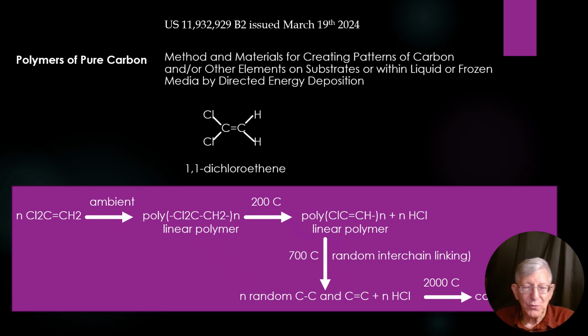Now, it turns out, and this is the part that intrigues us, that you don't have to heat these things to thousands of degrees to get rid of the HCl. If you heat it to, say, 200 degrees, this polymer, the dichloropolyethylene polymer, breaks down, splits out a mole of hydrochloric acid. For every monomer that went in there, you get an HCl out, and you end up with a linear polymer, which is a chloroethylene material. And when we realized that, we said, hey, we're almost home free here. We're going to make carbon nanotubes and graphene left and right. That's not quite the way it worked out.